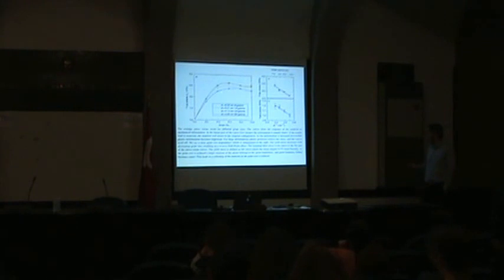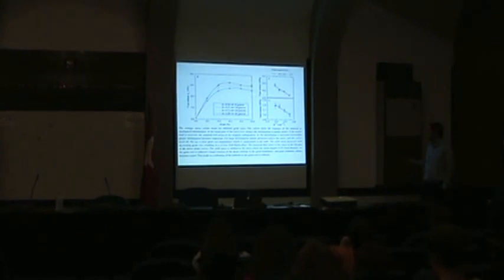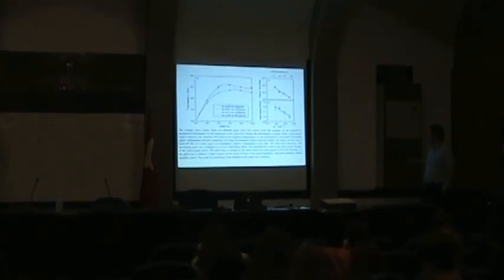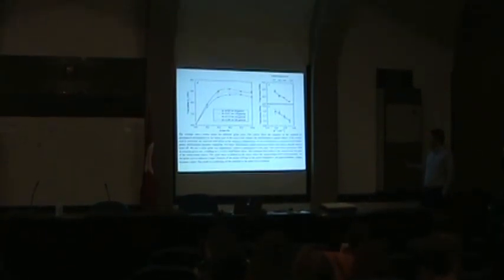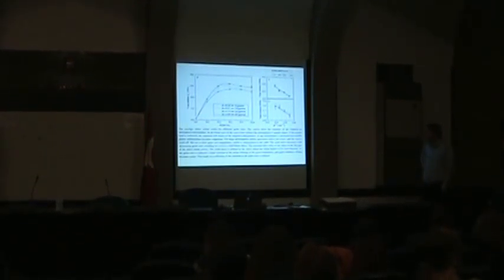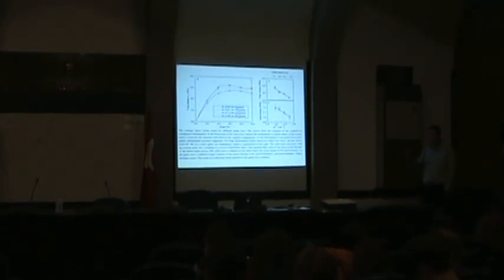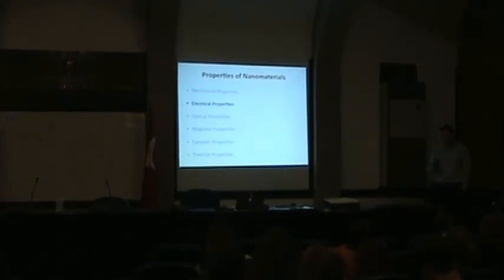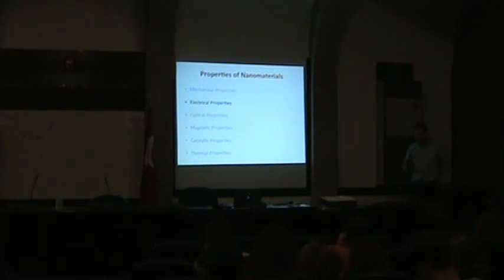So this is an extreme that I'm basically telling you guys. An example, this is probably from Ireland. Very difficult to find examples of these. As you do see in here, as the grain size decreases, the stress increases, both the flow stress and the yield stress. Here you go, the light blue, as you do see, the stress decreases with the grain size. And obviously this is an extreme, just to give you a flavor. So if you are to use it for mechanical applications, stay around 20 nanometers, 50 nanometers, where the Hall-Petch equation is still valid.